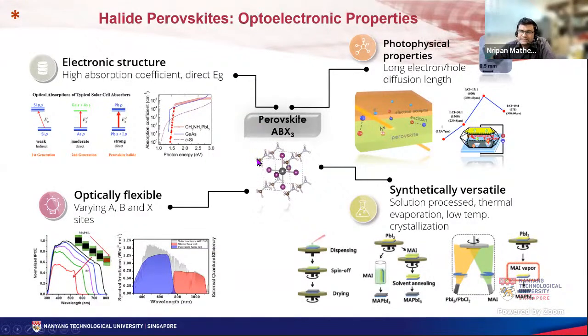The reason why it is exciting is because these systems are processed very simply. You do not need very high temperatures to form it, and you do not need super expensive equipment. Just like you spin coat your photoresist, you can spin coat and form this. You can evaporate and form it as well. And although they are formed by such rudimentary methods, the electronic properties are pretty good. The electron and hole transport lengths in these systems are pretty high, and because of the electronic structure, the absorption edge is very sharp. Sometimes we joke that it's like III-V semiconductors, but solution processed.